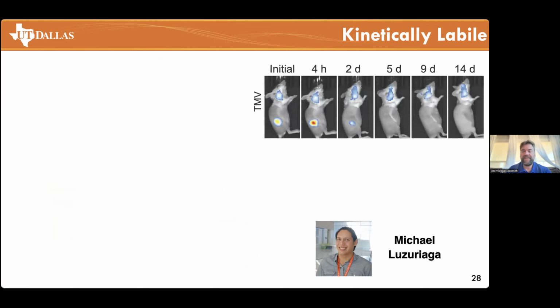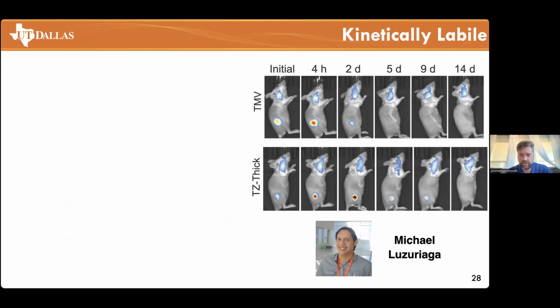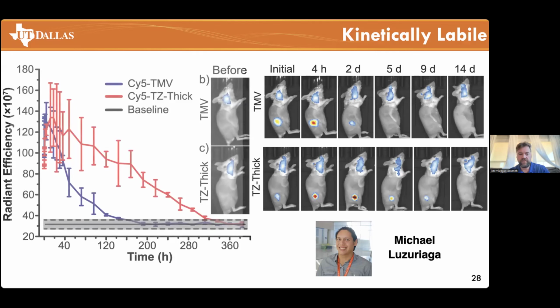And so if we compare this, we can look at this using the tobacco mosaic virus as a second example. If we just inject tobacco mosaic virus, this is much smaller. The immune system is not as keen to recognize it. It lasts at the injection site about 2 days. If we wrap it in the ZIF, you can see again, this one lasts longer, almost 9 days. And so again, we can show that even with a virus, we can retain them in tissues for much longer. And here is a radiant efficiency plot to illustrate the very large difference in retention time. So again, showing a depot effect.